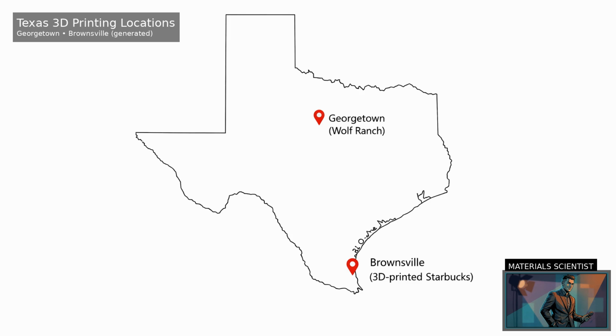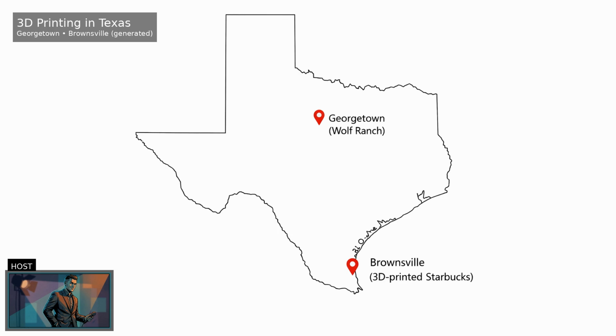Precisely, and we're seeing real projects. In Georgetown, Texas, the Wolf Ranch development is building 100 3D printed homes. And Starbucks opened its first 3D printed US store in Brownsville, Texas in May 2025. The caution is that printable mixes can be cement-rich to pump and set, so printed doesn't automatically mean lower carbon. If you use a high cement mix to print a wall, you might accidentally increase emissions, right?